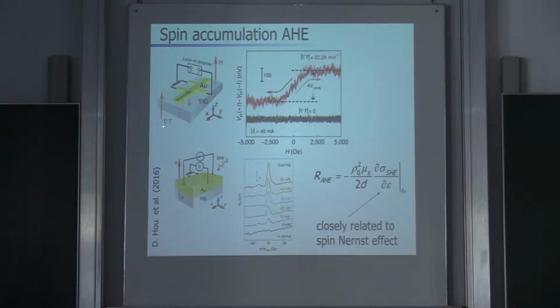So, under the conditions that there is a finite gradient, he is getting a probe current through the gold, and he measures indeed a Hall signal. He measures an anomalous Hall effect in gold, which is not magnetic in equilibrium. Now, this is a direct proof of the spin accumulation. Now, here's the experimental result, in which he shows that if you are reverting the magnetic field, indeed the signal also changes sign. And it is also not going linear through, it just becomes constant here. There's no effect at zero magnetic field, so there is no something like an equilibrium proximity effect either. Now, there's a similar experiment he is doing here with spin pumping, but that's not so important at this point.